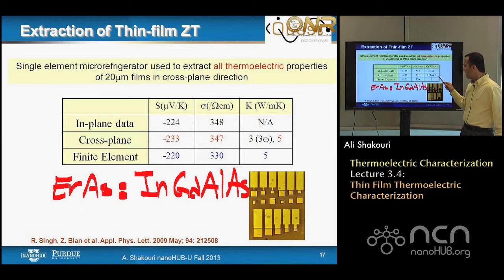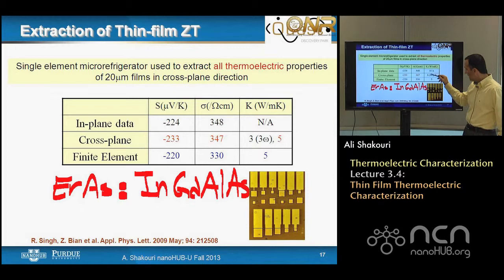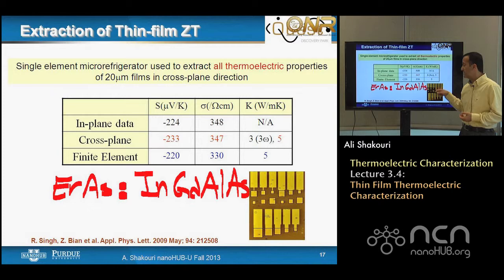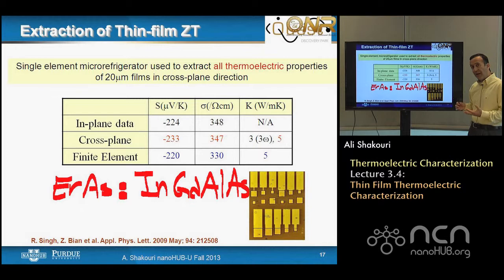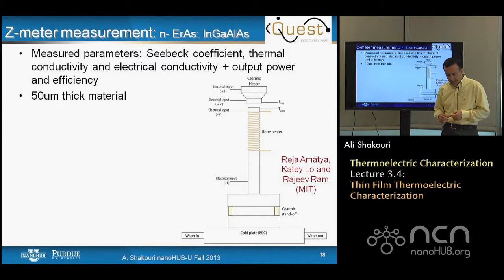There is a slight inconsistency: both cross-plane thermal conductivity data and finite element give a thermal conductivity of 5, while 3-omega measurements on thinner 1–2 micron films gave 3 — a discrepancy that could be film-to-film variation and remains an open question. The basic idea is that these micro-refrigerator devices allow you to get ZT directly, and because the optical thermoreflectance technique measures temperature on top of the device directly, you can separate individual components of ZT — which is very advantageous.